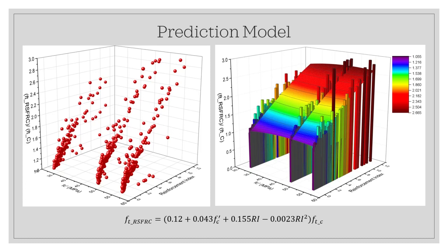One thing that I need to mention here, because as I said this research is still ongoing, is that RI, which is the reinforcement index, was defined here as a multiplication of shape factor by volume fraction by aspect ratio. What we found from this research was that RI really needs to be revised because the reinforcement index as defined is not really accurate. Of course, by simply considering it as a multiplication of these 3 parameters, we cannot get accurate results. So what we actually found was that the weight of each of these 3 parameters, shape factor, fiber content, and aspect ratio, is different in increasing the strength.